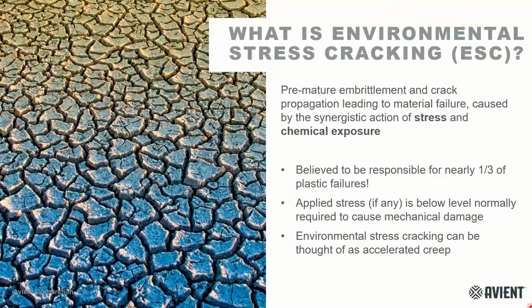So now I want to define what environmental stress cracking is. It's a premature embrittlement and crack propagation that leads to material failure, caused by the synergistic action of stress and chemical exposure. And the second part is really critical. It's the combination of stress and chemical exposure that really accelerates the timeline to failure. Just a few fun facts: environmental stress cracking is believed to be responsible for nearly a third, some literature says a quarter to a third, of all plastic failures. And another thing to note is that the applied stress, if any is applied, is often below the level which normally would cause mechanical damage.